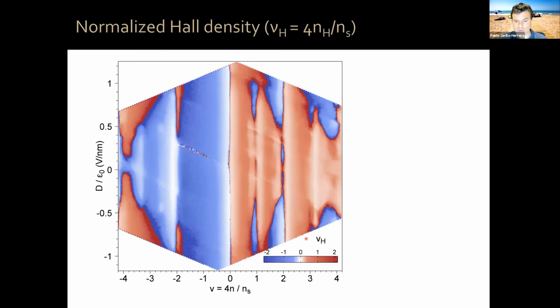So then when we measure this, we also have this complex phase diagram as a function of displacement field and filling factor. And to zeroth order, all of the features here can be associated with one of the following three situations. Okay? If you have a gapped Dirac point, your Hall density goes smoothly through zero and changes sign, because your density of carriers that can contribute to conduction, that's what your Hall density tells you, disappears at a gap point or a Dirac point, okay?